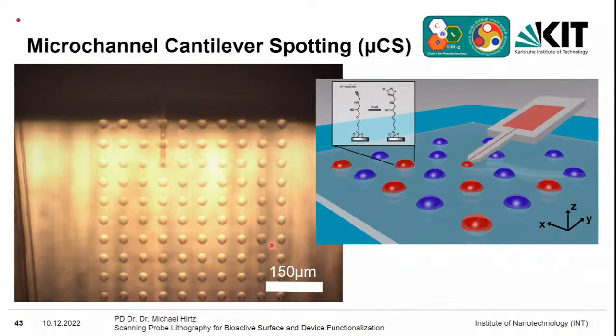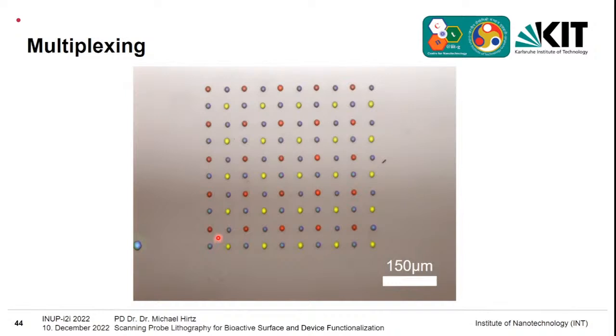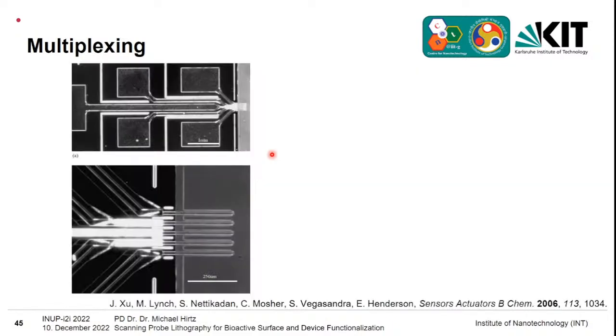And this is particularly neat because now you can do chemistry in these droplets. They are femtoliter sized and allow you to let wet chemical reactions happen in these small reaction vessels before you wash it away and you end up, for example, with the immobilized molecules from these reservoirs. You can also do multiplexing here. That means here, 3 different fluorophores were spotted next to each other. So you can have very tiny, neat arrays of different materials next to each other that are not that easily done with standard lithography methods.